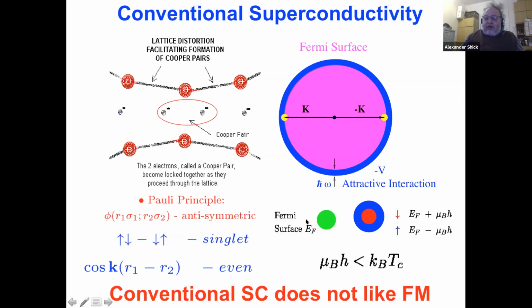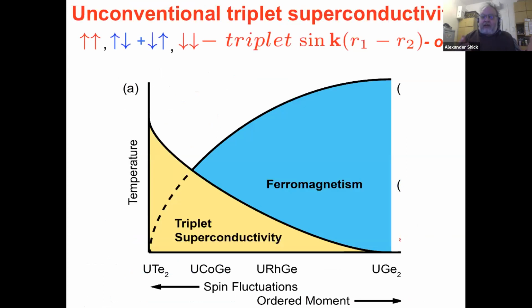And then, if you imagine what happens when you apply the field to this singlet, the Fermi surfaces, which were the same for up and down before the field, become different, so they shift. And if this shift is less than the superconducting TC, which measures the strength of the pairing interaction, then the superconductivity can survive it. But usually this shift is more than the superconducting TC. It means that conventional superconductivity is usually destroyed by magnetic order. Well, on the other hand, the spin part of the Cooper pair doesn't have to be antisymmetric. It could be symmetric, and in this case we have what is called triplet superconductivity. Then the spatial part indeed should be odd.